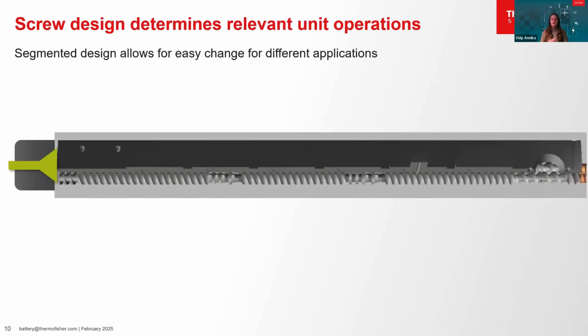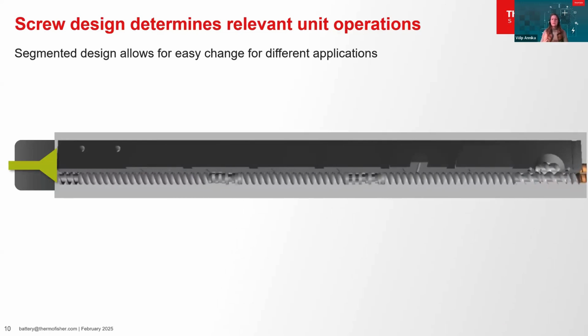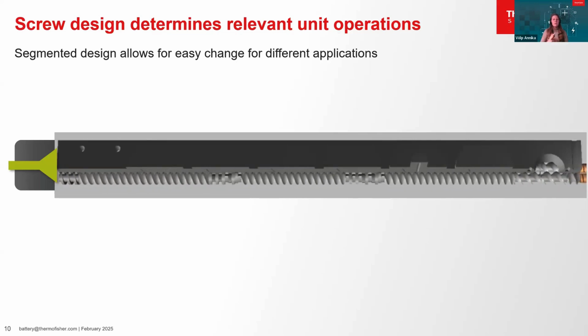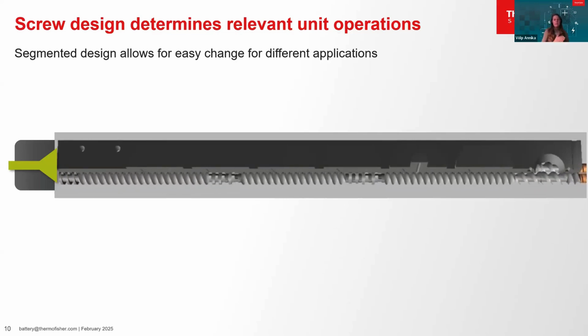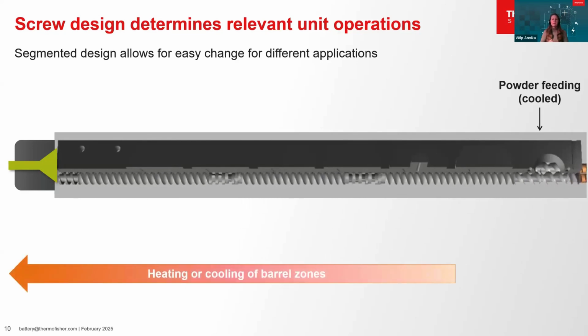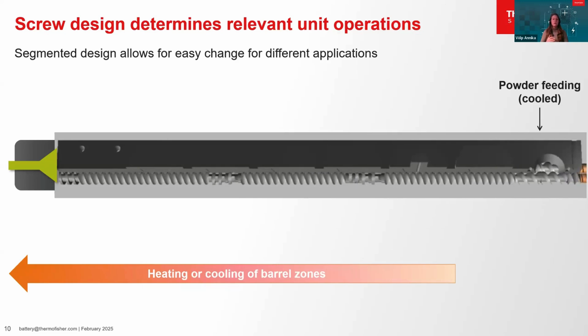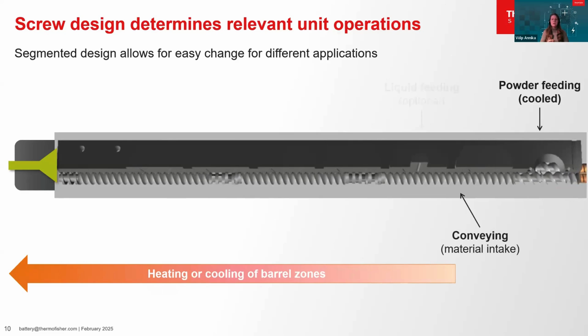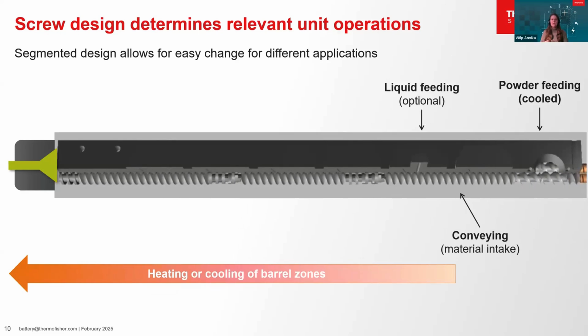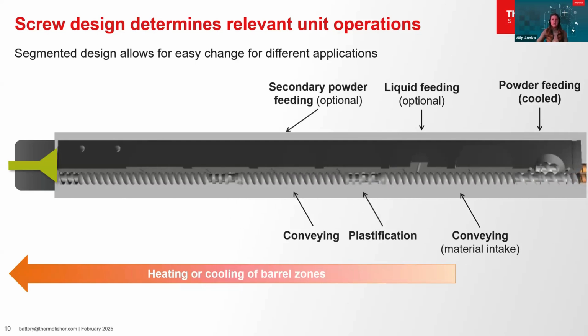This screw design of a parallel twin screw mixer is an example from polymer processing, and here it determines the material processing units from right to left. Powders are fed into the main feed onto the elements with a wide screw gap. This zone is cooled so that the powder does not melt and block the port. In the next barrel zones, a temperature profile is set to melt the material and control its viscosity. Next, there is a zone with conveying elements. Optionally, liquids may be fed into this zone.